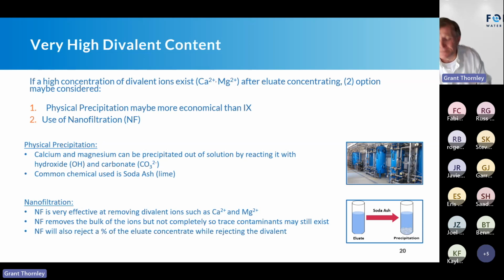So it's not only important the loading of the resin, but because you're going to be regenerating so often, the regeneration cycle becomes even more important than the actual loading itself. So if it's very high, we typically want to avoid ion exchange because the regeneration cycles are going to be very, very short. You're going to load fast, which means you're going to be going through a lot of regeneration, which means you're also going to be using reagents to regen with. So now my chemical consumption has gone up and my chemical waste stream volume is going to go up. So that's why I've said another option is physical precipitation. You can do it with ion exchange, but the economics of it may dictate physical precipitation.